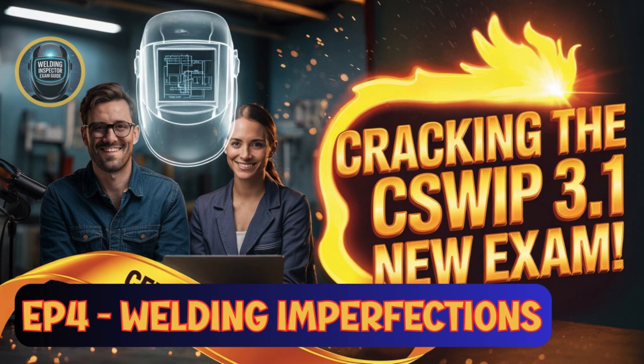It really does. Okay. Next on our list, lack of fusion and penetration. This sounds like the most fundamental problem you can have, the pieces just not sticking together properly. That's the core issue, yeah. Lack of fusion is quite simply a failure of union, either between the weld metal and the parent metal at the side of the joint, or between successive layers of weld metal in a multi-pass weld. Okay, so it can happen in different places. Right. We talk about lack of sidewall fusion, lack of interrun fusion between the weld beads, and lack of root fusion right at the very bottom or root of the weld joint.